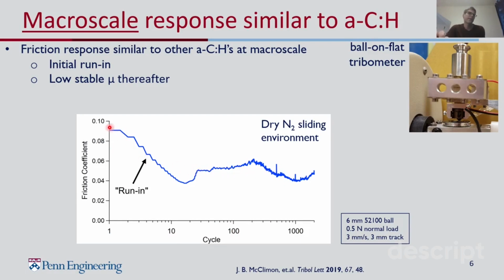It starts out with an elevated friction coefficient, and then over some small number of sliding cycles, we'll have a reduction in that friction coefficient, and that's what's referred to universally in the literature as the run-in effect. And then after that's complete, it settles in at a relatively constant steady state for thousands of sliding cycles. And the absolute value of the friction coefficient is very low, below 0.1. And this is typical for hydrogenated amorphous carbons sliding in inert environments. And in this case, the sliding environment was dry nitrogen. So that's the response at macroscale.